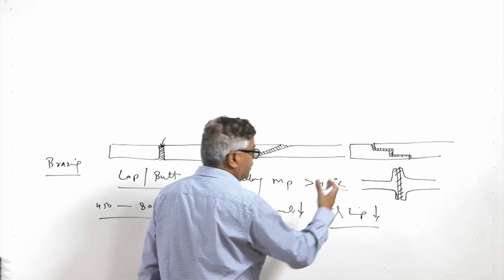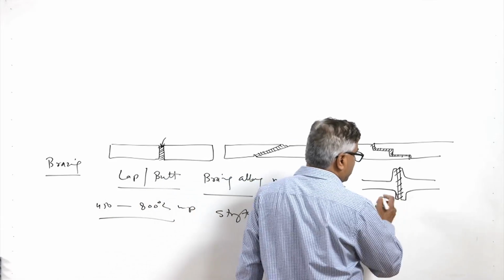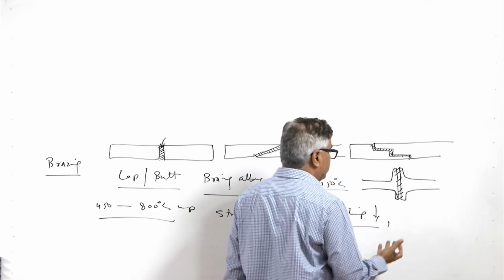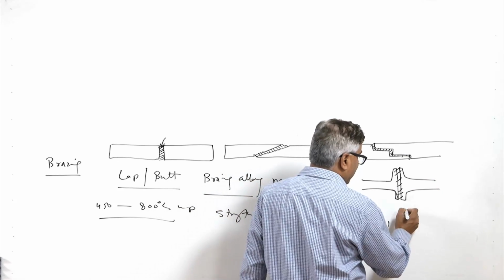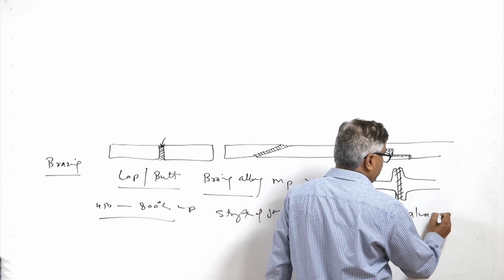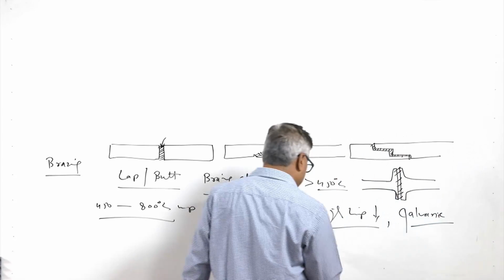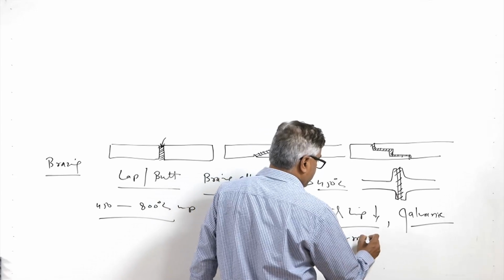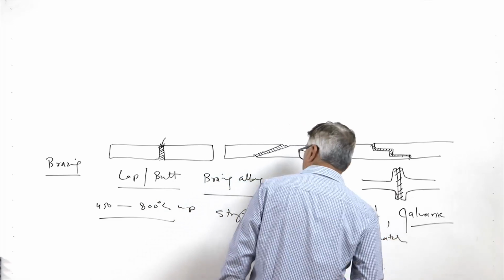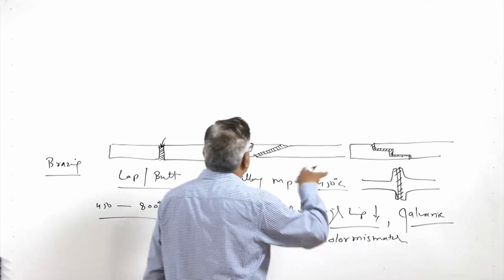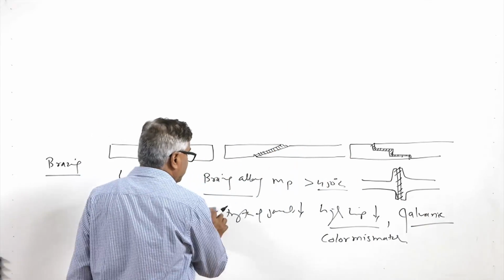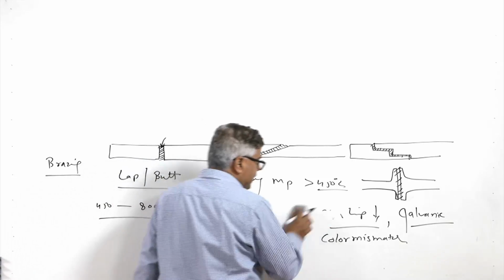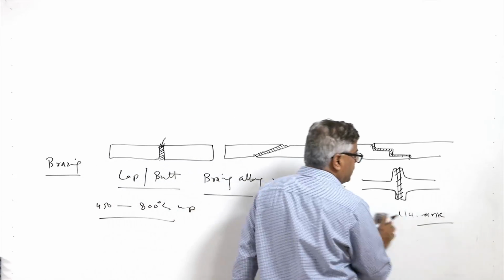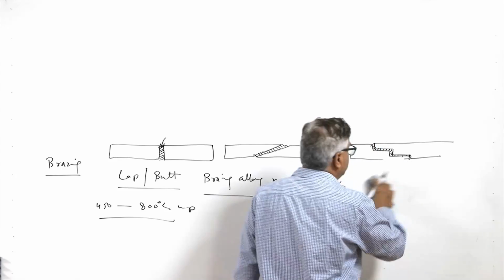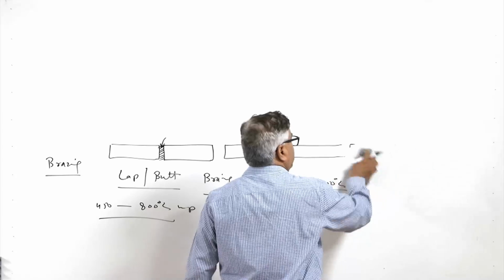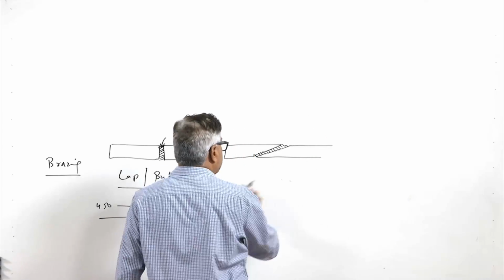They cannot withstand high temperature, and because the brazing material is different from the parent material, galvanic corrosion is promoted by this, and even color mismatch is also observed when the brazing is performed. So these are some negative aspects apart from the benefits which are produced, like the joint is made with a reasonable strength without melting of the base metal, limited heat input, limited size of the heat affected zone. So there are so many beneficial aspects related to brazing.